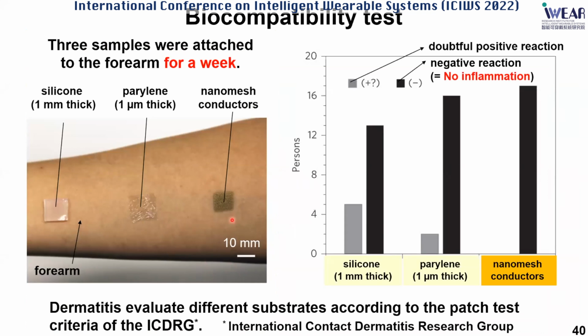Indeed, when nanomesh is put on people's forearm for a week continuously, the nanomesh doesn't cause any doubtful inflammatory issues. However, if 1 micron thick parylene or 1 millimeter thick silicone is put on the forearm for a week as a reference sample, that exhibits a fairly large risk of inflammatory issues.